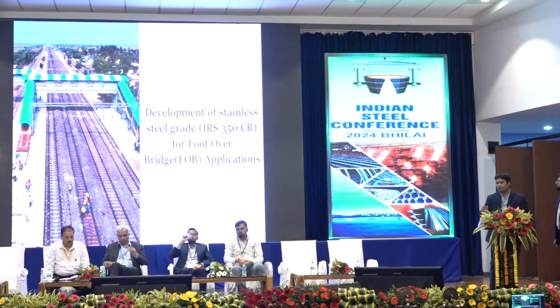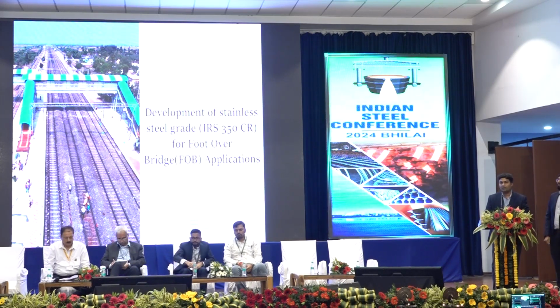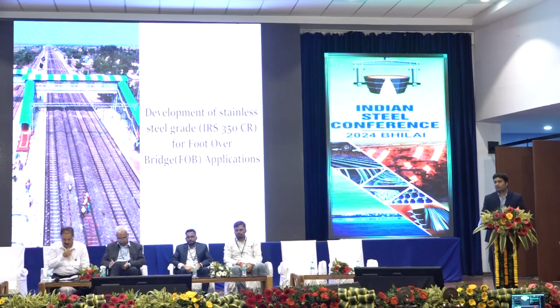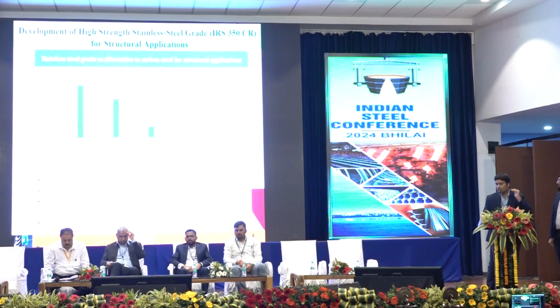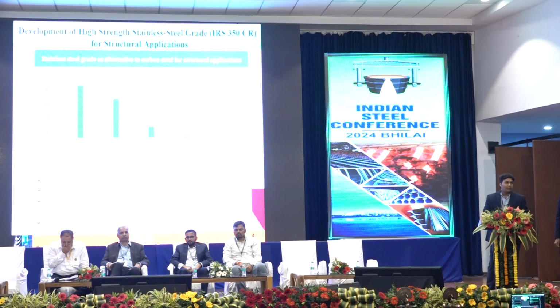You can see in the picture, presently most of the foot over bridges are made from carbon steel, low carbon steel with high strength, which has a higher corrosion rate compared to stainless steel. So, they require regular periodic maintenance, and there are a few places where maintenance is not possible. We apply coating, we apply paint, but that has a lower shelf life or lower life cycle.